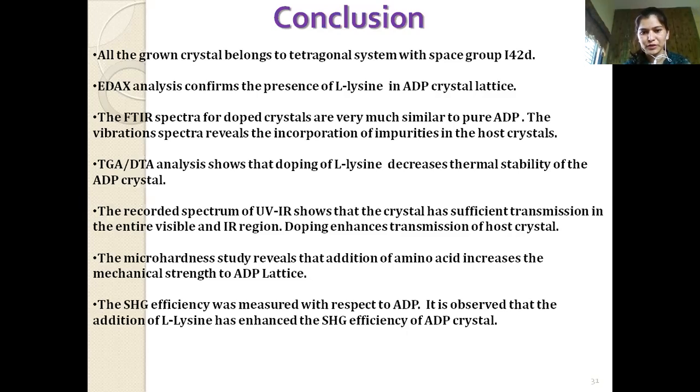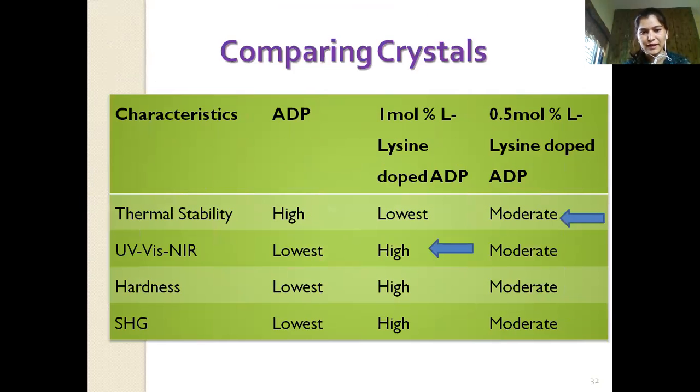Now, comparing all these three crystals for device application, we can say that the 1% lysine doped ADP is the best for device application in the electro-optics industry, because it possesses good transmission, higher mechanical strength, and a good NLO coefficient, if thermal stability is not the point of concern.